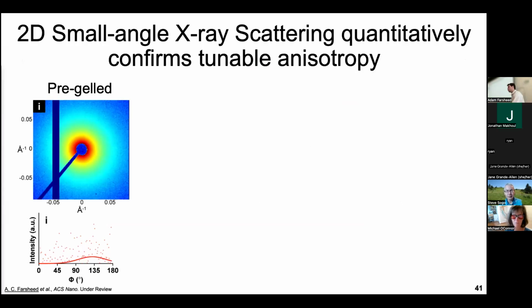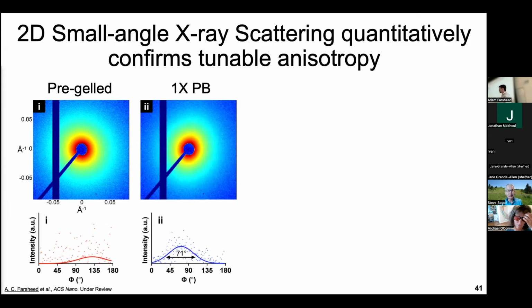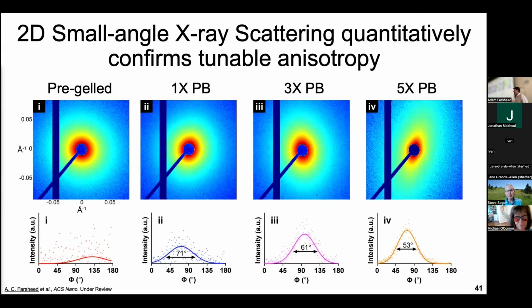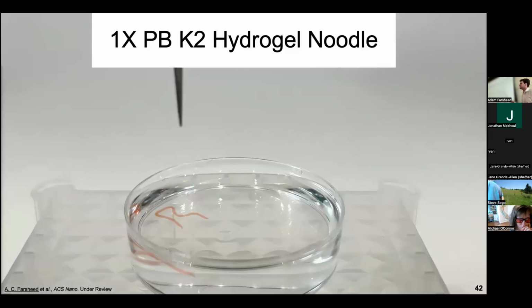So next, after all of those qualitative assessments, we turn to a quantitative technique called 2D small angle X-ray scattering, where you're basically observing the diffraction pattern of shining X-rays at your specimen. And so these bright images on the top are just what that pattern looks like. And at the bottom, I've graphed, as a function of the angle around that diffraction pattern, what the intensity of the signal is. And so again, as we go from left to right, we'll see an increase in that bottom quantification of this pattern. And in the top, it'll look less and less like a circle and more pointed. And so again, this is quantitatively showing us that this alignment that we thought we saw is actually the case.